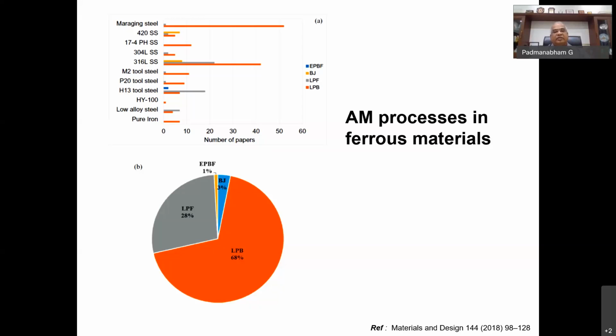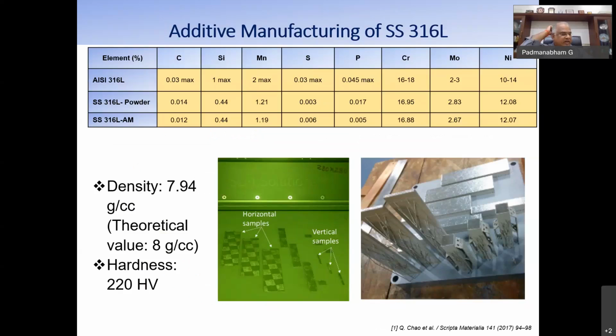And then you have laser powder fusion methods also used substantially. And within that, if you see the bar chart of the number of research papers, Maraging steel has the highest number of publications. And then the stainless steel. These are all well-studied materials, so a lot of applications are also there in these materials only. And the reason is, take the case of 316L. It's an austenitic stainless steel, a single phase material. Single austenite phase is there. And then density is achievable as theoretical almost, 7.94 versus 8 grams per cc.